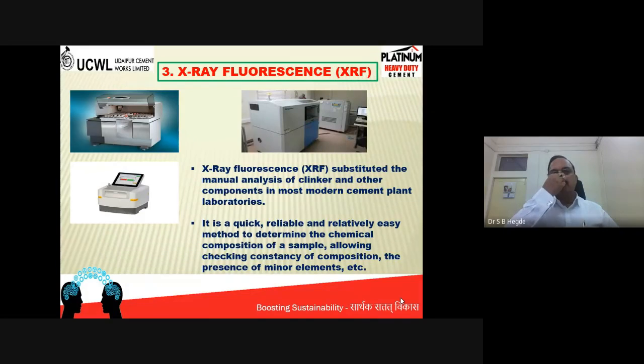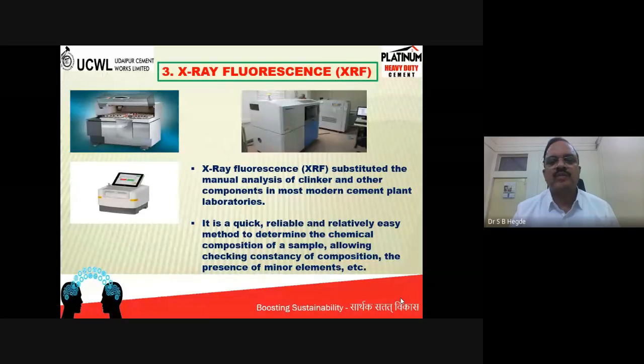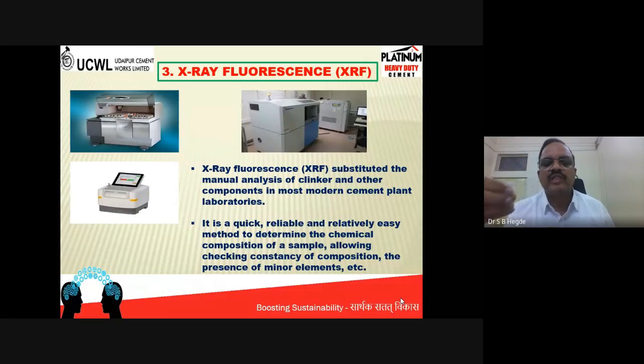So as I mentioned here, the X-ray fluorescence is used for finding out the oxide composition: what is the lime, CaO, SiO2, Al2O3, Fe2O3, and even some sodium, potassium, and any trace elements. These will be analyzed in the X-ray fluorescence within 5 minutes. One sample will take not less than 4 or 5 minutes. If you are going by wet analysis in the conventional laboratory, it takes around 4 to 5 hours for one sample.